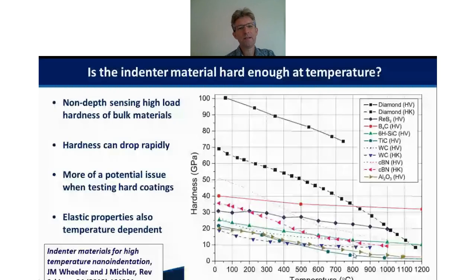So we test these materials with CBN, and this has been fine typically over the years, but as coating designers have got better, we're worrying a little bit about the wear of the CBN indenter. So we're asking the question: is the indenter hard enough at high temperature? Diamond, typically its hardness drops, but not too much. Other materials typically have lower hardness, and the hardness drops as the temperature increases. And this can become a potential issue if we're testing hard coatings that remain appreciably hard at high temperature.